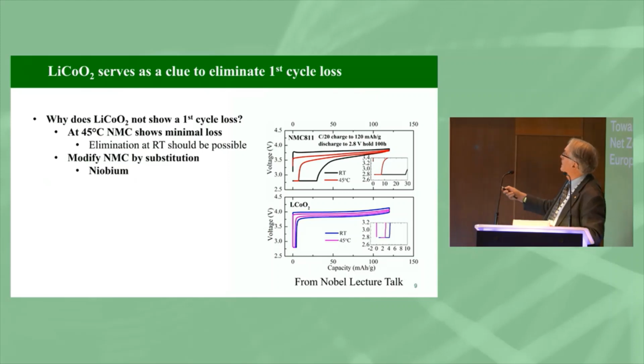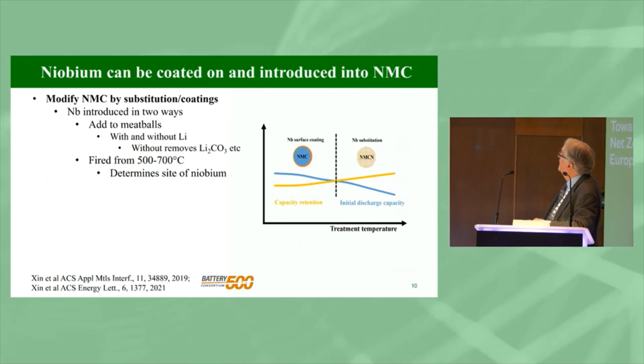And we've been modifying it by using niobium. We chose niobium because lithium niobium oxides are good ionic conductors. So if we put a film of niobium oxide on the surface, the lithium ion should still be able to get through that film. Unlike a standard method of, say, putting aluminum coating on where you've got aluminum oxide and it will increase the resistance. So what we've done is modified our material both by coating and by substitution.